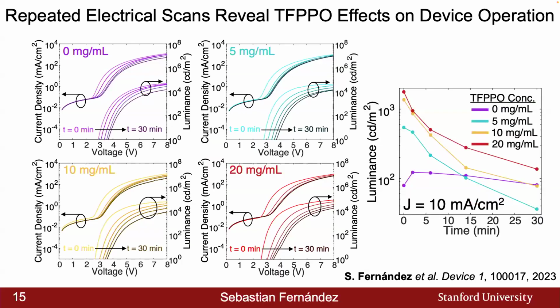If we look at the operational luminance, which is the luminance of the device at 10 milliamps per centimeter squared, we can see that the non-TFPPO treated device starts at a lower luminance, but does sustain that luminance for a little bit longer, and at time equals 30 is actually the more efficient device as compared to the 5 and 10 mg per mL device. And I would argue if we extended this measurement out even further, it might become more efficient than the 20 mg per mL device as well.